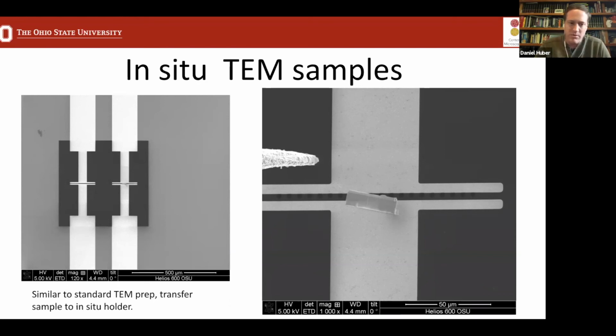So this is a sample that I produced for a collaborator in Chicago. And so this is a biasing holder where there's a piezoelectric material in the foil, and the top and bottom of the foil are actually being biased at different potentials. And the thin area underneath the platinum cap where the piezo material is existing is now lined up over top of very small windows in between the two electrodes. And so the group that was doing this work was able to directly observe the piezoelectric effect in the material by applying a bias and actually seeing the atomic columns move. So it's pretty exciting to work on that.